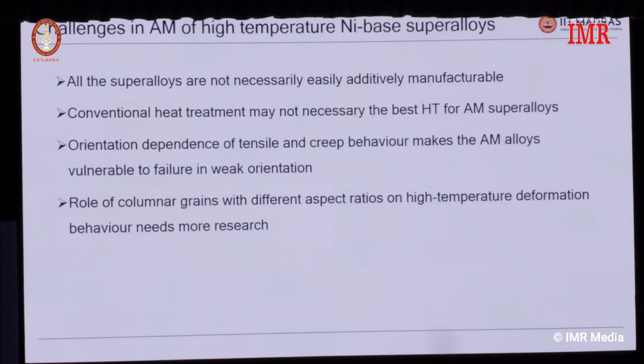In the last slide of the talk, about the challenges in additive manufacturing of high temperature nickel based superalloys, we have to understand that not all superalloys are easily additively manufacturable, so we have to tweak the parameters to print them. Conventional heat treatment, traditionally used for cast or wrought products, may not necessarily be best for additively manufactured nickel based superalloys. There is a build orientation dependence of their properties, both high temperature and creep properties, that needs to be studied. And the role of columnar grains with different aspect ratios in high temperature deformation needs much more research.